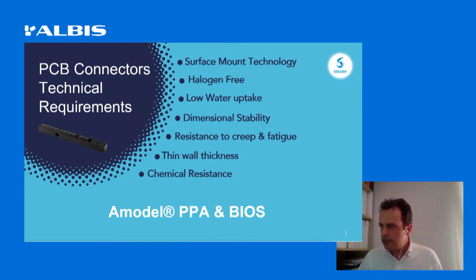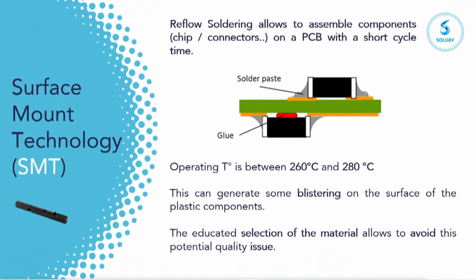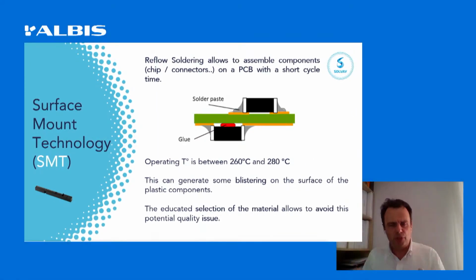Go to the click here, sorry. Before to enter into the material detail, let me explain or dig a bit deeper into two concepts. First, the surface mount technology, SMT. When car makers, when customer wants to assemble electronic components on a PCB, in most of the cases, they use a technology which is so-called reflow soldering. Reflow soldering allows to work with a very short cycle time. But this technology operates at high temperature, between 260 and 280 degrees C. Time to time, it can go up to 305 degrees C during a couple of minutes. So it's quite an important temperature.